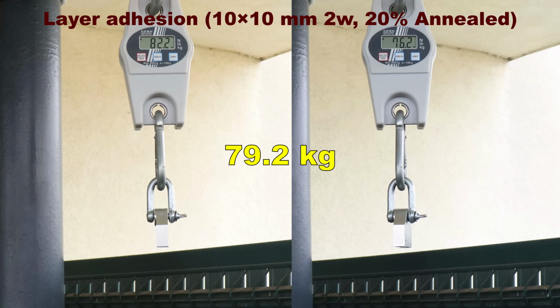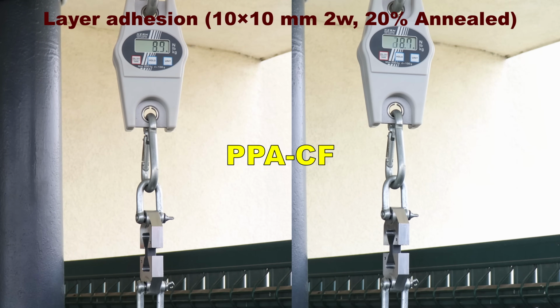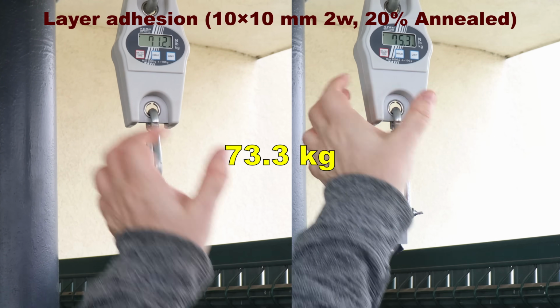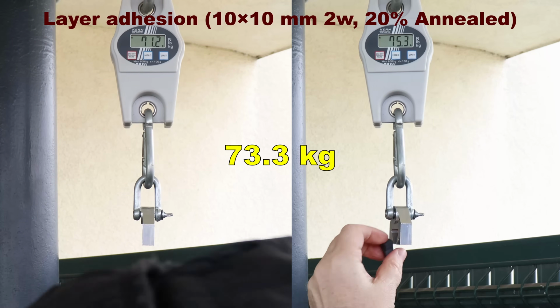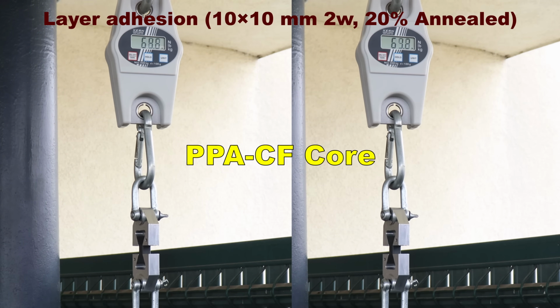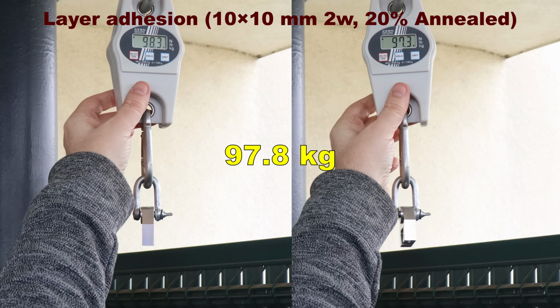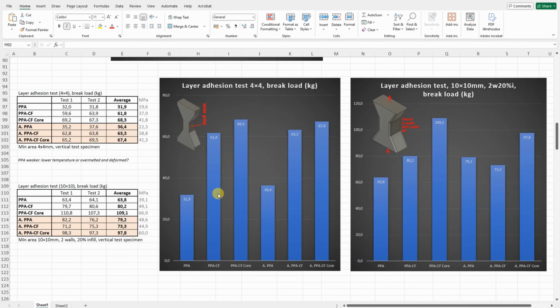This time very good. Carbon fiber version, still very good. And the core, extremely strong. The first conclusion here that annealing didn't significantly change the layer adhesion. Well, one exception I have here with the PPA, from some reason here it was better.